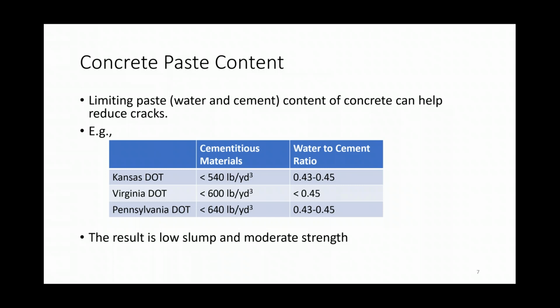Okay, so the first thing we really discussed was, what makes a concrete mix crack less. And one thing that really came out was the paste content of the mix. It looks like for these modern mixes that have less cracks, the paste content is limited. If you limit the paste content, which would be water and cement content, it does seem to result in fewer cracks. And of course, you also get a moderate strength, but the consensus was that we don't really need a terribly high amount of strength for concrete bridge decks anyways.